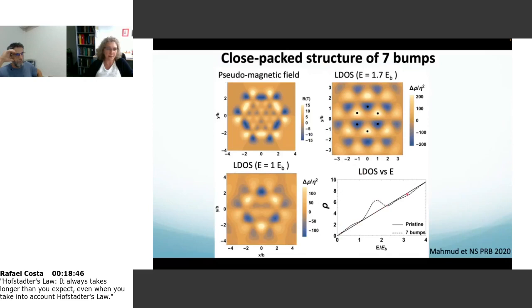The pristine graphene will have a linear density of states. With bumps, the density of states will have a bump at a particular energy, which tells me that there is an accumulation of states, or accumulation of charge if these states are occupied, at particular energies. And that brings to mind, maybe I can localize these. Maybe I can create individual local quantum dot regions inside graphene.